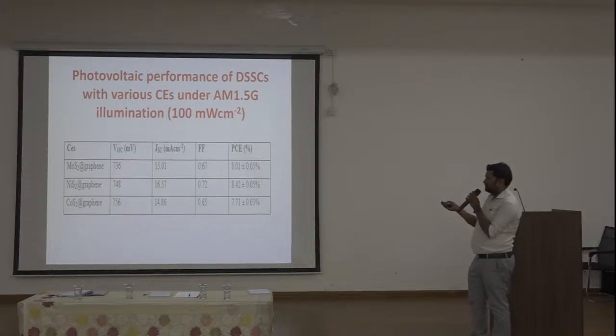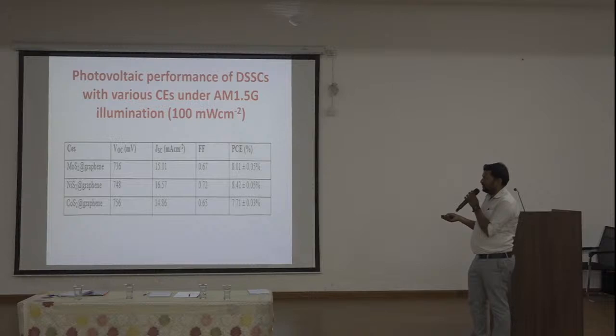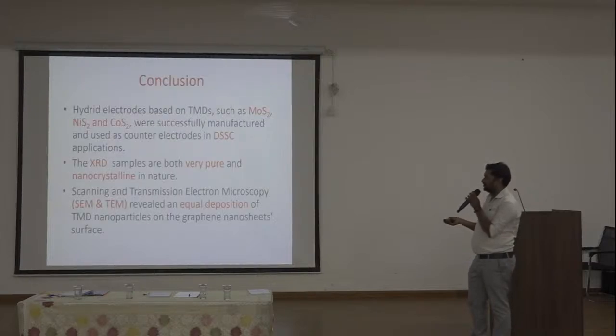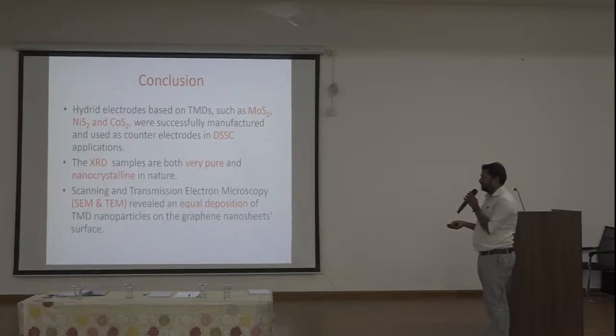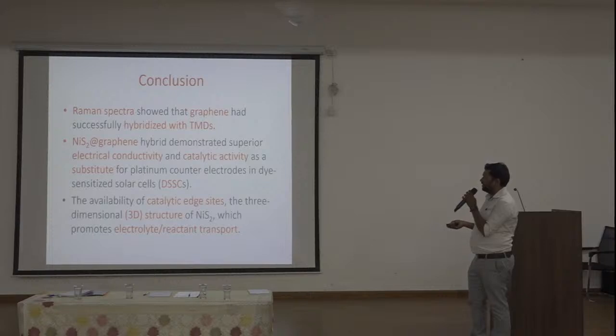So overall, nickel disulfide is the best performer among the counter electrode materials. So NiS2 is one of the best counter electrodes for platinum-free DSCs. This is the conclusion of the overall presentation. We prepared 3 different types of TMD material for DSC application. XRD reveals the pure nanocrystalline structure, SEM and TEM reveal uniform deposition, and Raman spectra show the graphene had successfully hybridized with the TMD material.